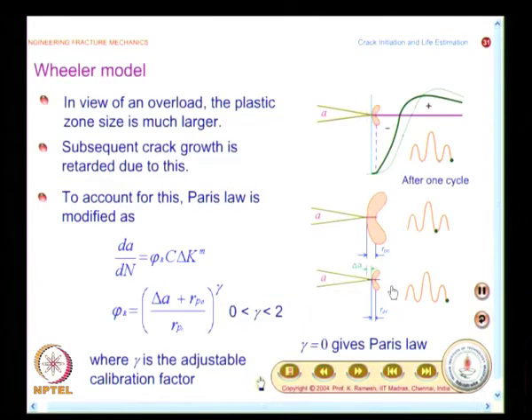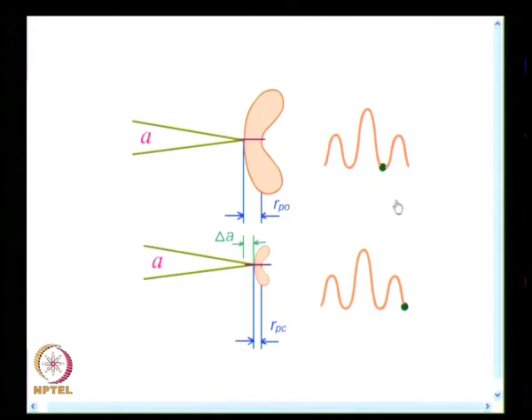And that is what is depicted here. You have along the crack axis, whatever is the length of the overload plastic zone is given by the symbol RP overload, that is O. When you have a normal cyclical load, the plastic zone is smaller. I think I will try to magnify it. I hope it comes within the screen. Okay. So, you have it here. So, I have the definition of these terminologies. I have a small crack length extension because of one cycle of load, that is given as delta A.